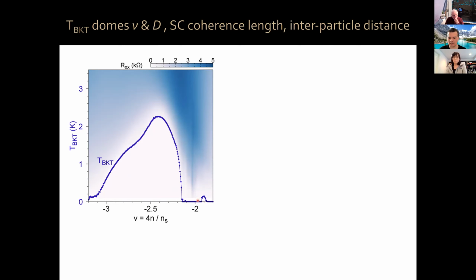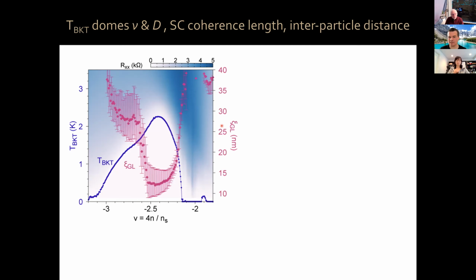As you can see, there is a very small dome for electrons and a much bigger dome for holes. This is around 2 holes per Moiré unit cell. Now, in this same plot, I can show you the superconducting Ginzburg-Landau coherence length that we measured as a function of density. It decreases as you reach optimal doping, and then it increases.